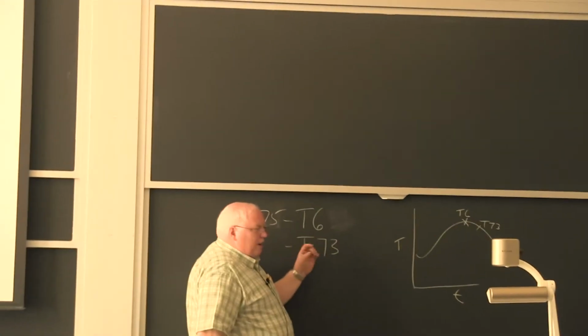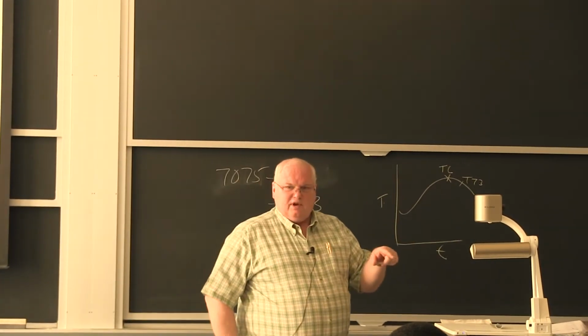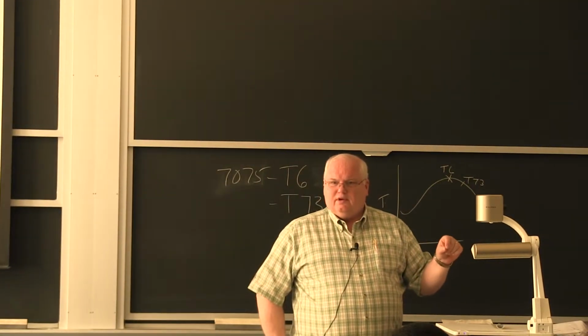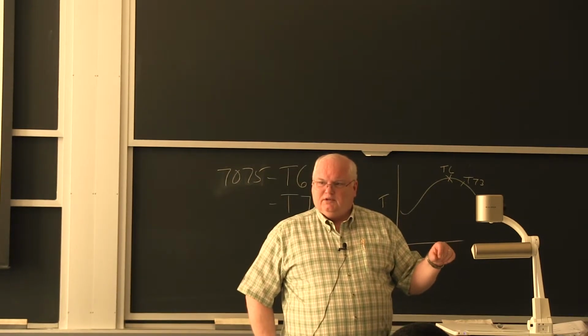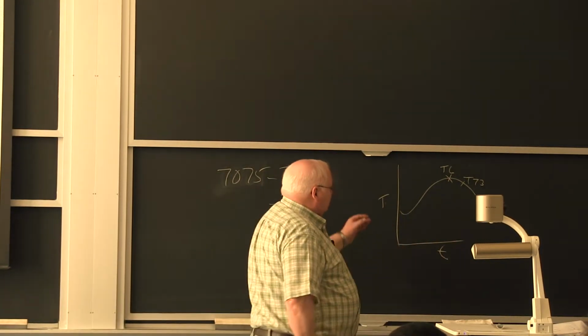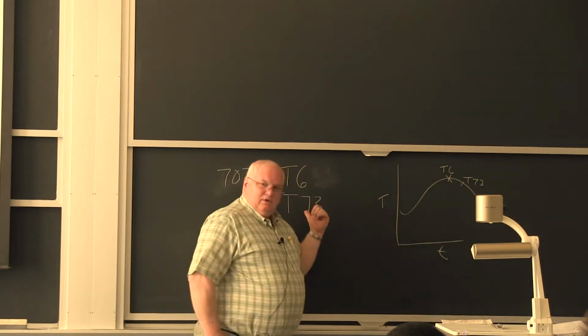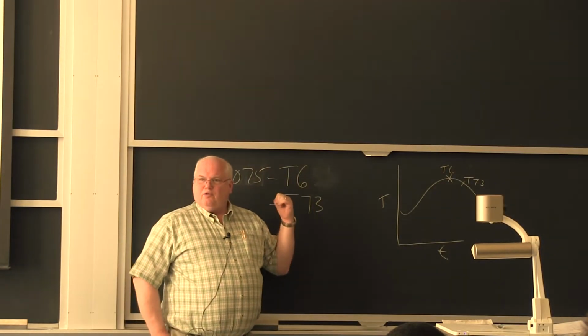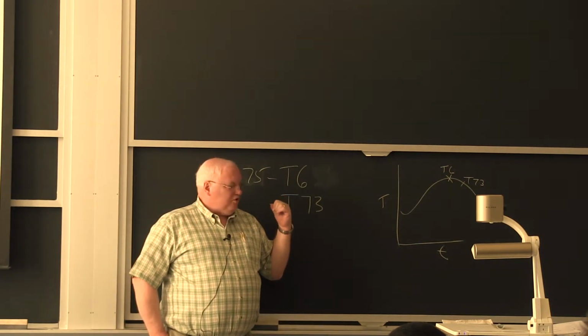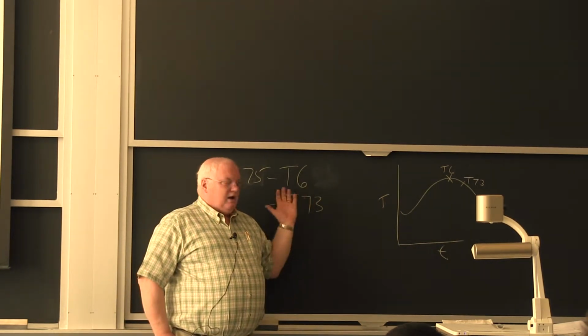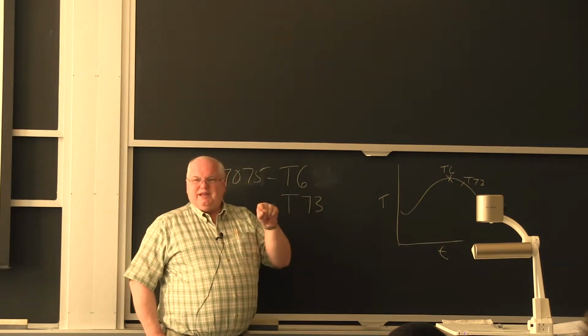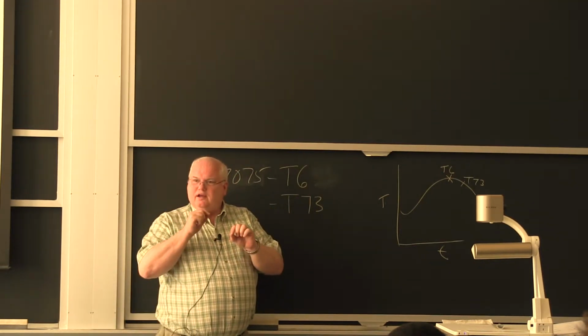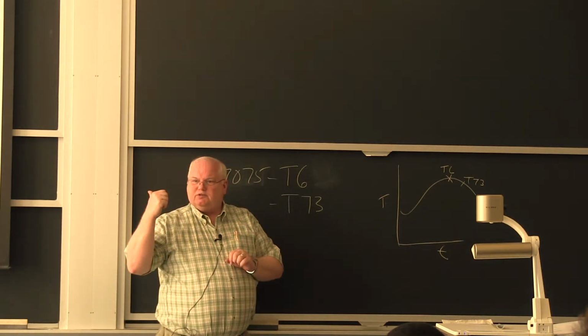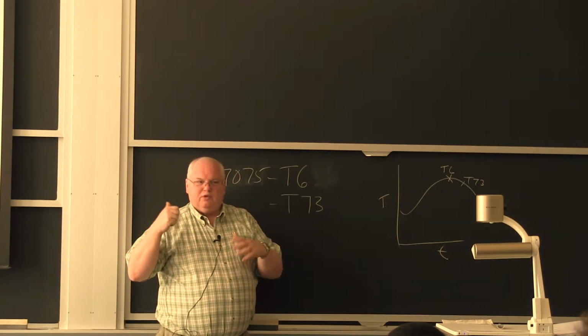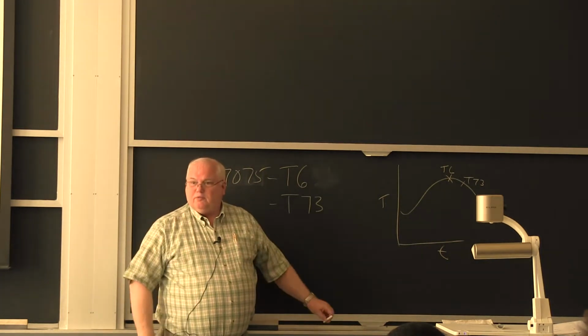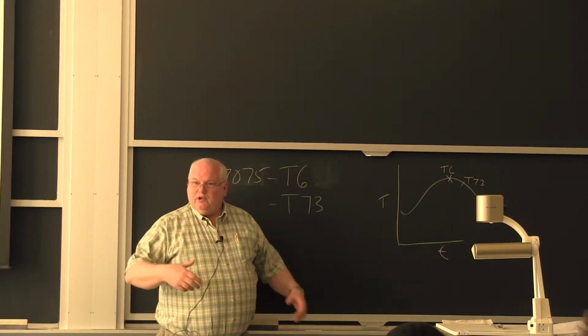But in fact, the solution to his problem was, that was like only 1/8 of an inch thick, to go from 3 millimeters thick to 4 millimeters thick, to increase the wall a little bit, because we're going to get less strength, but we could double our fracture toughness or our stress corrosion cracking threshold. And with that, we made it into a leak before break. So when the crack went all the way through, it would just spray out a little stream of oil, and people get all oily, but they wouldn't get shrapnel going through them, okay? So you don't mind being oily because you got slickers on anyway.